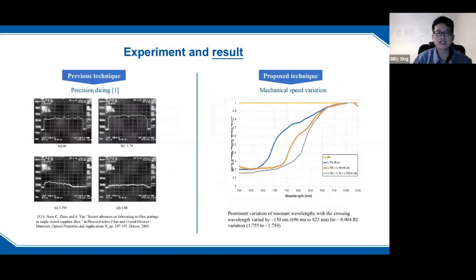Compared to the previous technique using the precision dicing method, we also used the same approach, adding the index oil to see if the fabricated grating is effective. The result there is not that obvious. Compared to our results, you can see an overall intensity drop, but after you increase the refractive index, you don't see a particular region drop. So in this proposed technique, we observed a prominent variation of the resonant wavelengths, with wavelengths varied by 130.